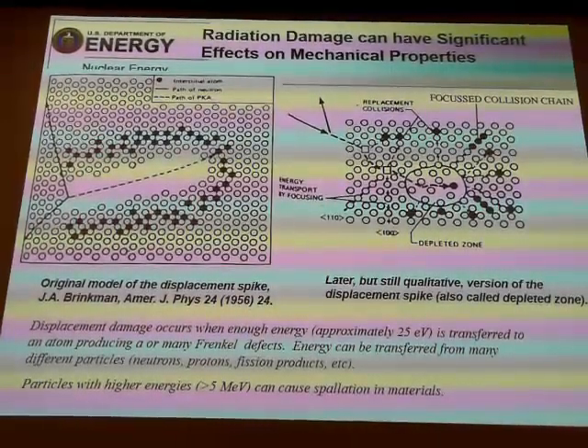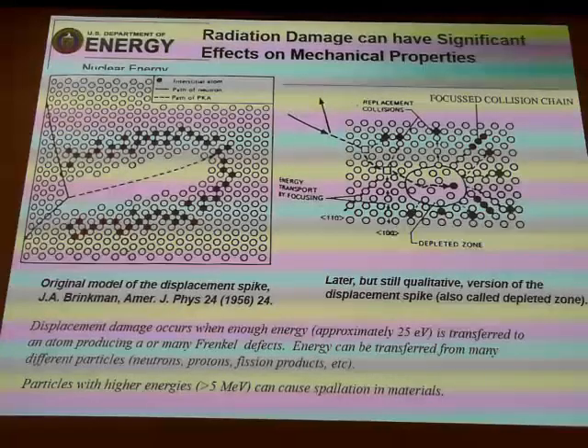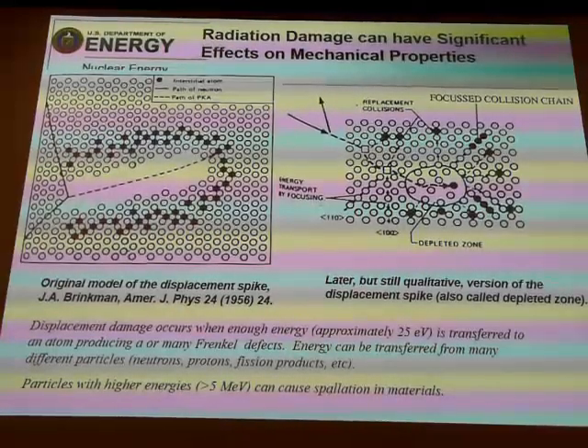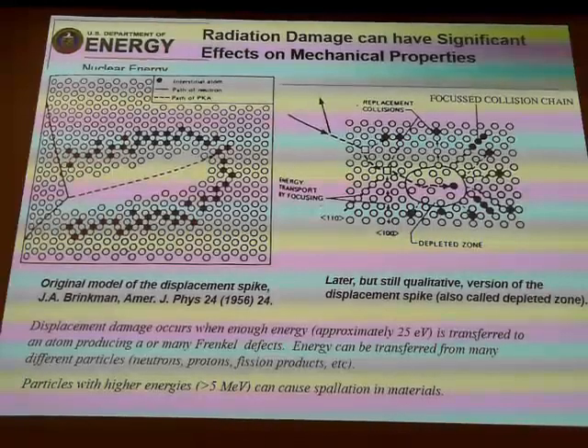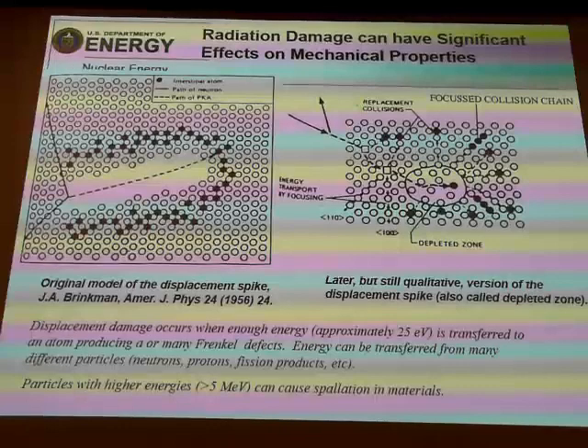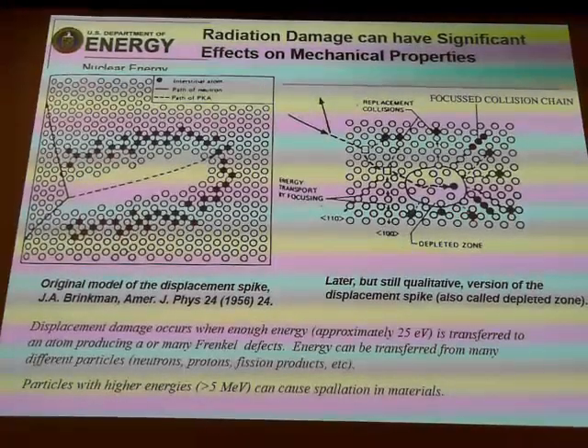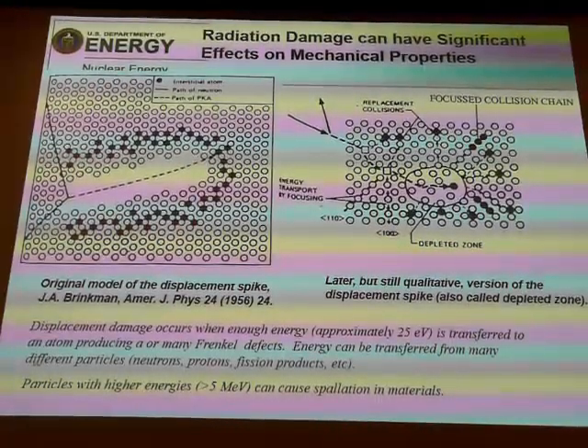And of course, that's happening continuously under high dose of radiation, and eventually can build up a large number of defects, interstitial and vacancy clusters, which eventually lead to dislocations and maybe also precipitating out new phases, and can lead to changes in material properties. And we want to be able to know that, be able to predict that, and be able to develop the best materials that can resist that sort of radiation damage under high doses.